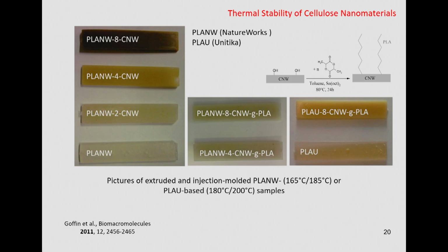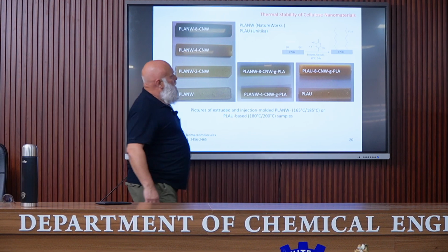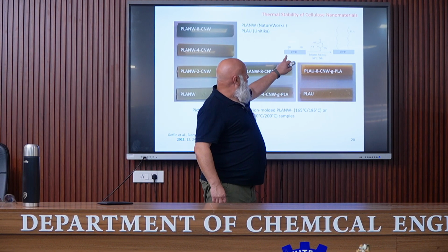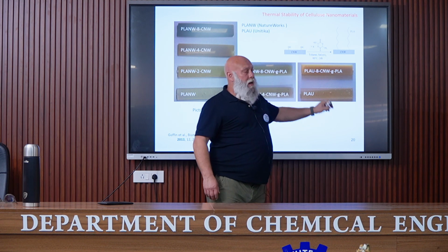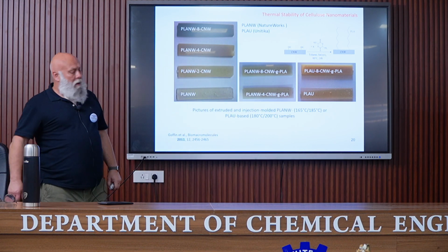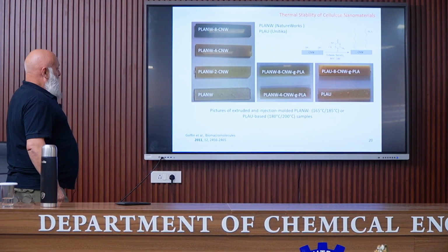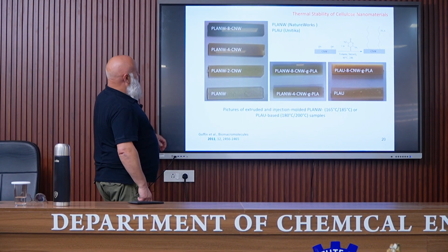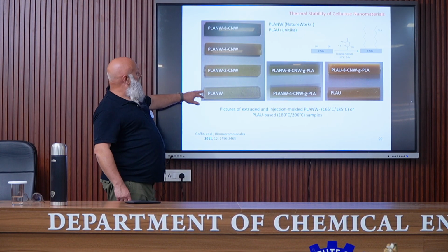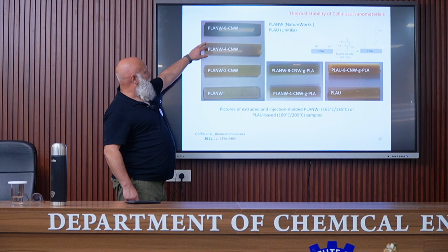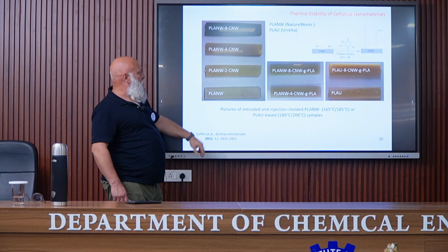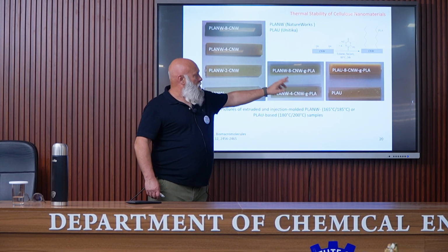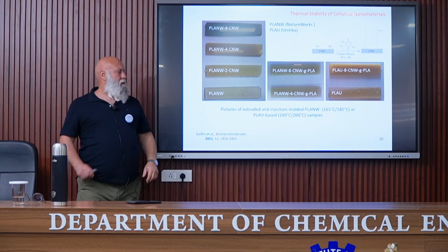So this is another example in which cellulose nanocrystals have been grafted with two different PLA, also with a grafting-from approach. And you can see the samples that have been obtained. This is for unmodified nanocrystals, 2%, 4% to 8%. You can see the thermal degradation. And after modification, we can see that the degradation is much less.